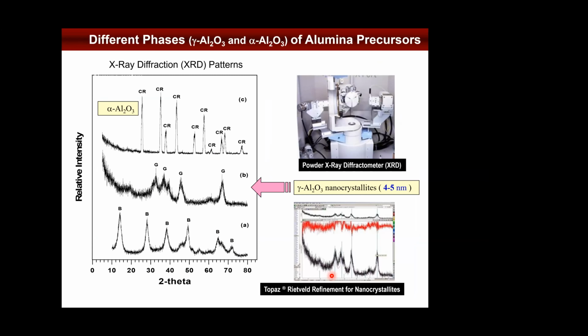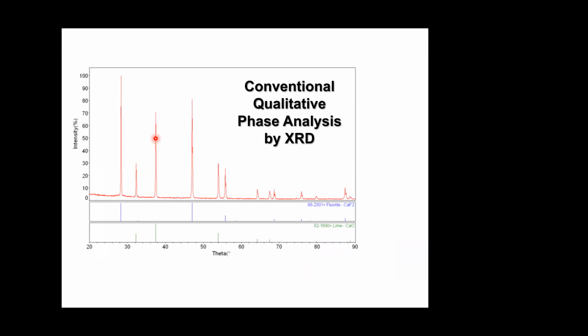So first of all, as a lot of people understand, in the thermal treatment process, when the clay is transformed into different phases, you may have gamma alumina, but gamma alumina, together with so-called alpha alumina, or corundum, has exactly the same chemical composition, Al2O3. But on X-ray diffraction, they have completely different structures. When we have different structures, we have different X-ray diffraction patterns, and we can use the so-called standard pattern to fit them. For example, if you have an X-ray diffraction profile right here, what you usually do is take the standard pattern and try to fit that.